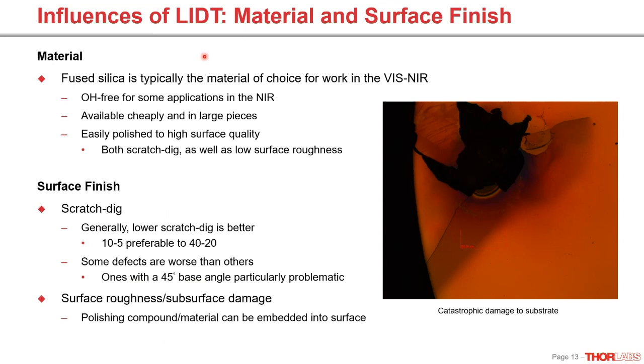Obviously, we strive to make defect-free surfaces, but some defects in terms of laser damage are worse than others. If you have a 45 degree base angle in the center of the aperture, that's going to be problematic. If you have a very light scratch outside of the clear aperture, that's probably not going to be an issue. And the reason the 45 degree base angle is going to be less than ideal is that's going to have some focusing effects. And that's something to avoid.